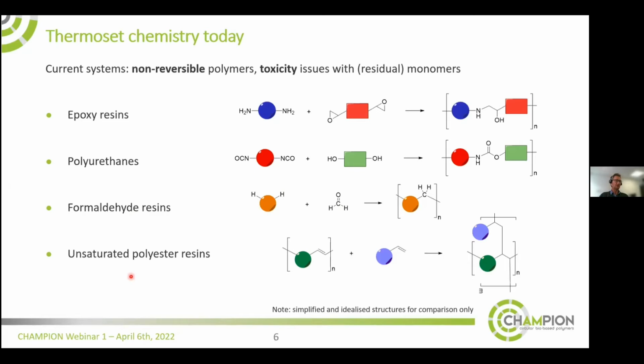And finally, there's a big class of thermosets called unsaturated polyester resins. In this case, you take a polyester resin with activated double bonds and you react it with a reactive diluent. In almost all cases, this is styrene. And then you end up with a strongly cross-linked network. And these materials are used a lot also in composite materials.